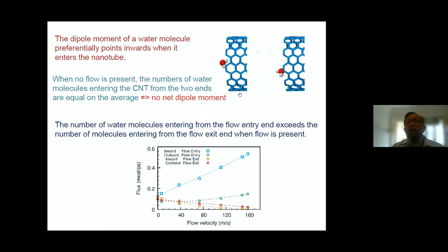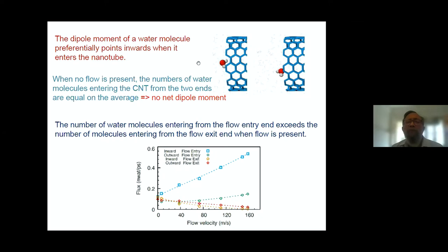The reason for this net dipole moment production is the following. We now look at water molecules which are entering into the nanotube. The water molecule can go inside with its dipole moment pointing inwards or outwards — these are the two situations. Surprisingly, what we found was that the water molecule has a propensity to go in with its dipole moment pointing inwards. So there is a preference that when the water molecules go into the nanotube, more often than not, the dipole moment will be pointing inwards.